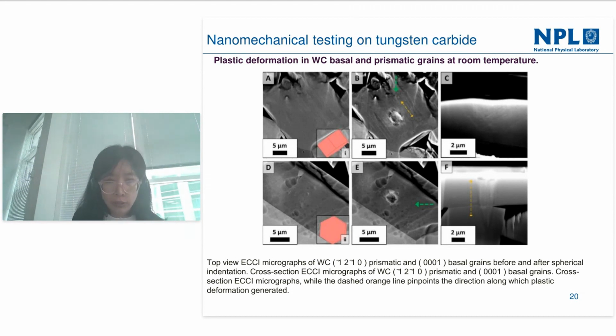The cross section on the prismatic orientation shows the impact of the different slip planes, which form an angle of about 120 degrees. And for the basal plane, you can see the dislocations mainly glide downwards along the 1010 plane system. So these are the quasi-static load results.